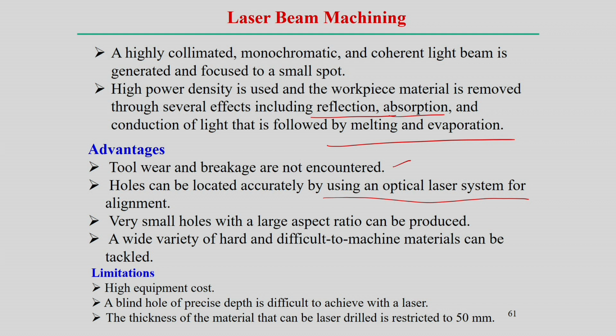Small holes with a large aspect ratio can be produced in these cases, and very hard, difficult-to-machine materials can be tackled using laser beam machining. But the main limitations are the high equipment cost, and a blind hole of precise depth is very difficult to achieve using a laser. Of course, the depth of penetration is limited; at maximum it can reach 50 millimeters.